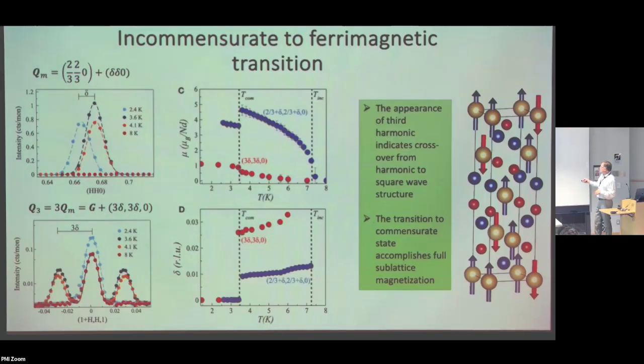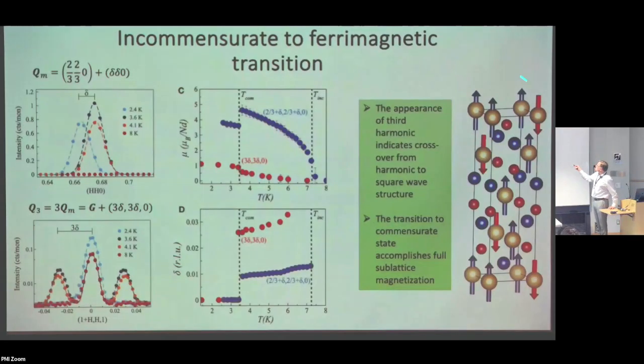And it basically has two spins up and one spin down, and there's therefore a net magnetization that's present. I should say that I'm going to slightly update this structure. This is a somewhat simplified version of it, because all of these spins have a little bit of a canting associated with them. They're rocking a little bit back and forth, and that rocking is very clear experimentally. We have no doubt that it exists. And that is actually a very important part of the magnetic structure that we do associate with the Weyl nature of the underlying band structure, because that has to do with the presence of a Dzyaloshinskii-Moriya interaction, which is driven by the lack of inversion symmetry, and comes in as a result of the Weyl physics.